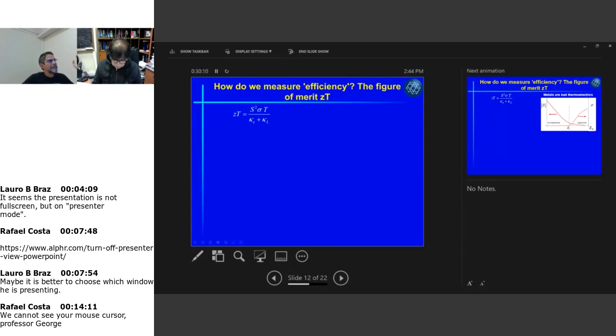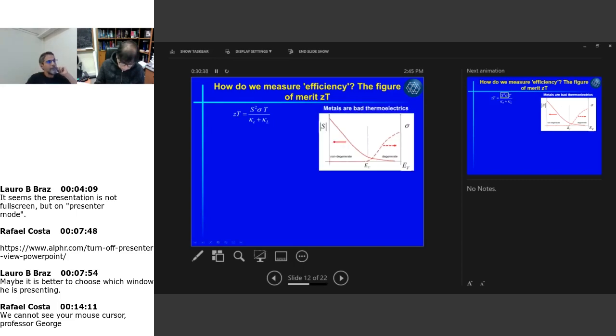And here it is a little bit less clear why it's S squared times sigma. Obviously, you need to have conductivity. An insulator is not going to be a good thermoelectric, because you are not going to have charge carriers. So you have to have a conductor, but it cannot be a very good conductor. We're going to see in this slide, this is for a semiconductor. So here on the left side, we have a non-degenerate semiconductor, or in other words, a lightly doped semiconductor. On the right side, you have a degenerate semiconductor, a heavily doped semiconductor.